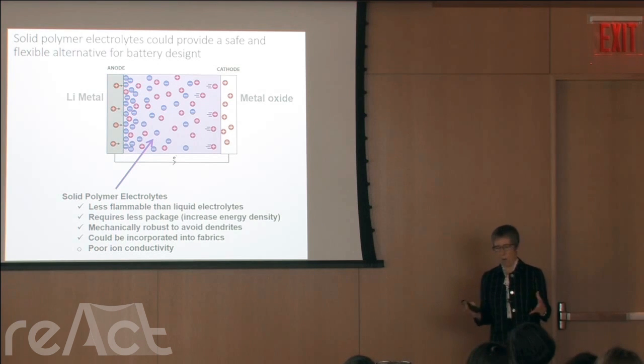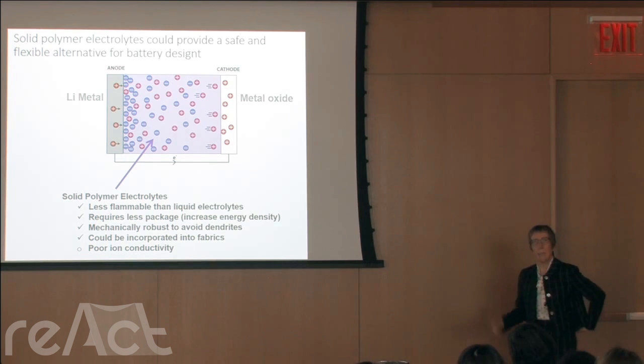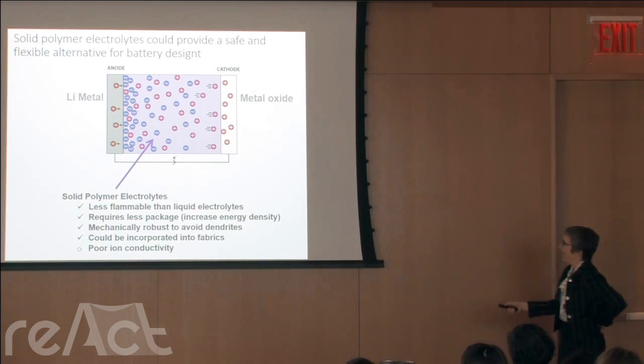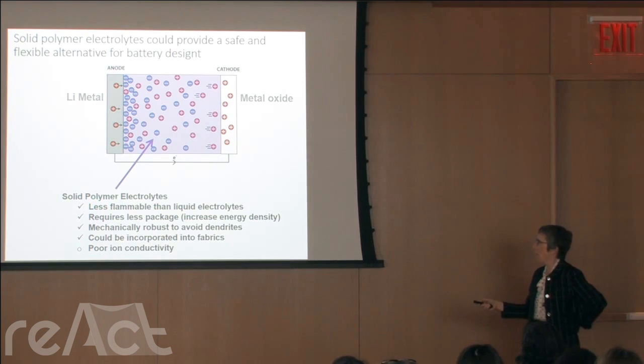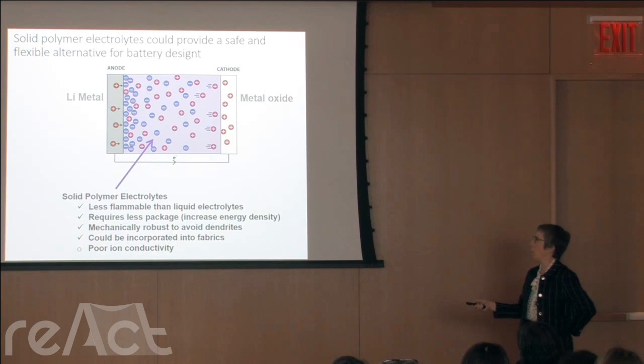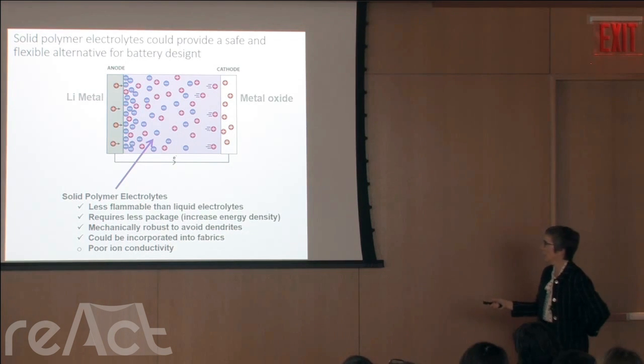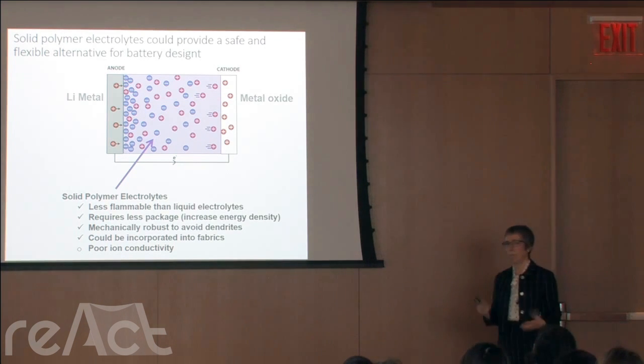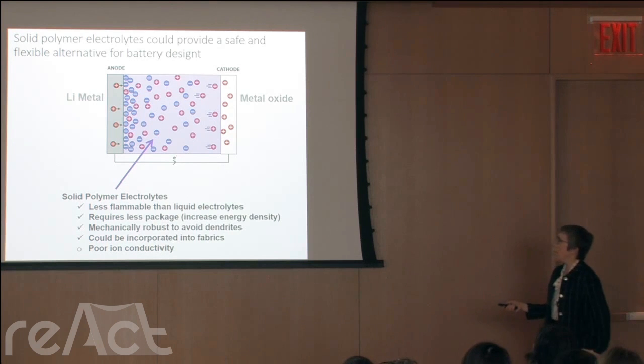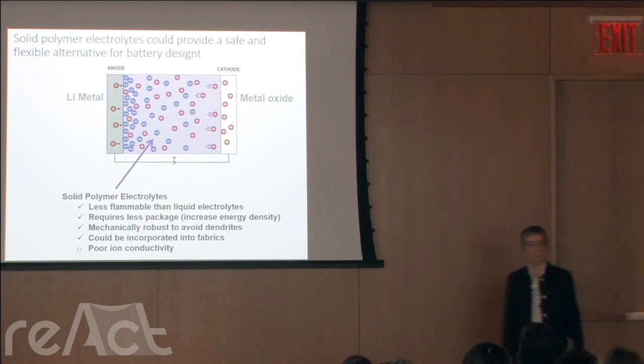You have a high polarity solvent and you dissolve your salt in it. It just hasn't been working very well. But the advantages nonetheless of moving to solid polymer electrolytes are that they will be less flammable, so they will require less packaging. It'll prevent the formation of the dendrites that short out the circuit. And it could be incorporated into fabrics or tent poles. But to date, the conductivity has just been lousy by a couple orders of magnitude. Right? They're just not viable yet.